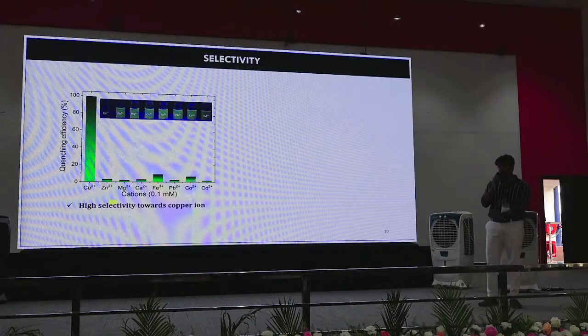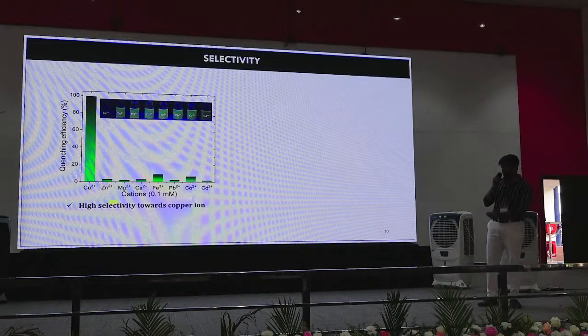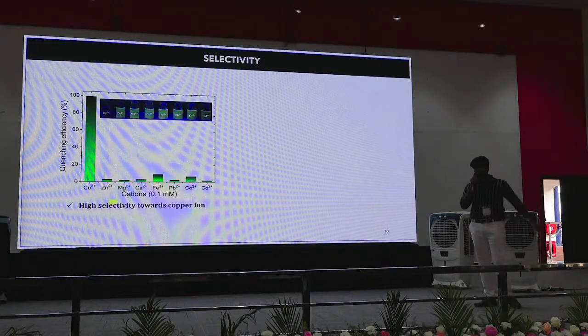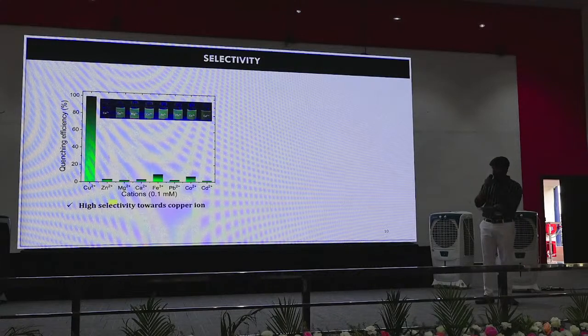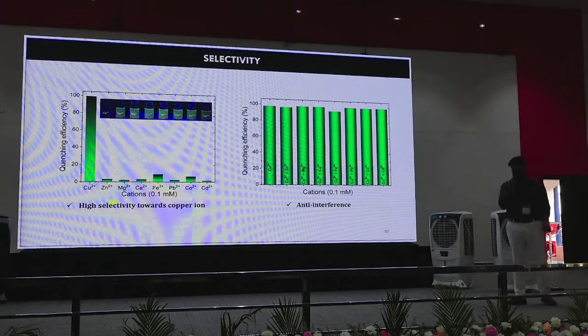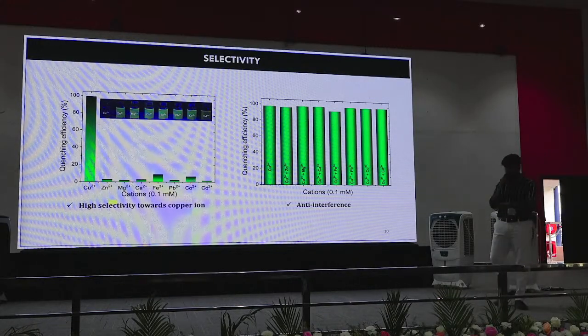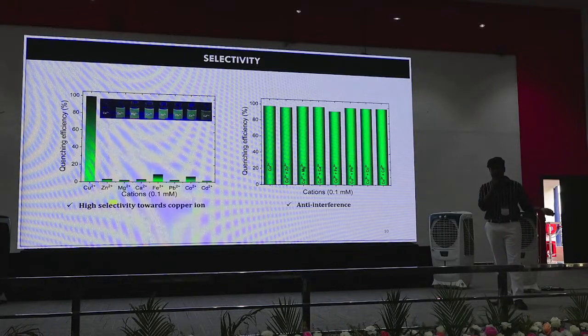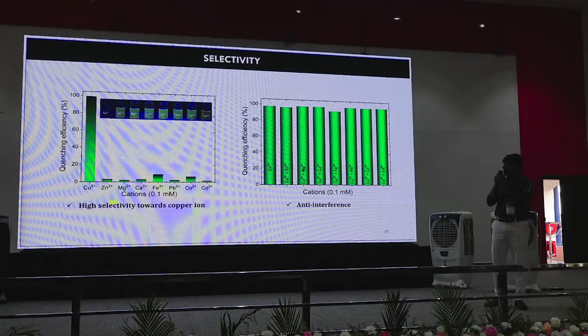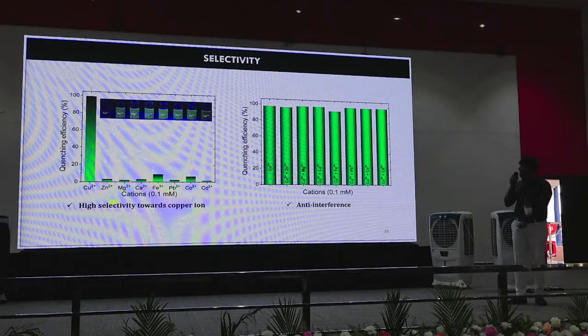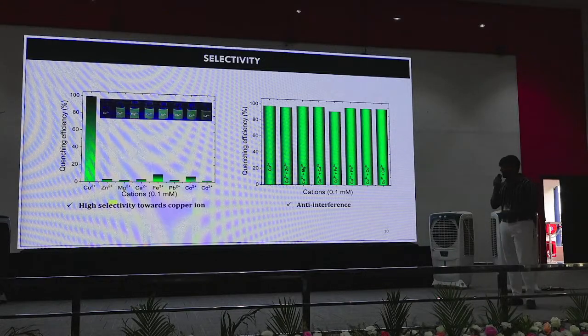For the application part, we designed this as a copper sensor, so we utilized it, and it is highly selective towards copper. As you can see in the plot, copper has the highest quenching efficiency. In the inset image also you can see that only copper has quenched the fluorescence intensity, not any other cation. And we also did an anti-interference study, because if you are going to use this in a practical application, you can't just say my sample should only contain one cation, right? It might contain various cations. My probe will specifically detect only copper. So we did anti-interference studies, and the quenching efficiency of copper is not reduced, as expected.